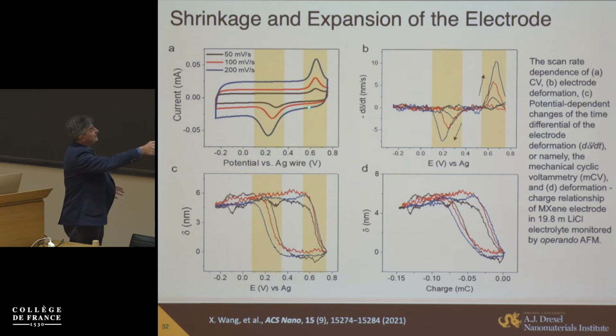And then when potential decreases to roughly 0.4 volt, starting here, they go in again, opening the structure in a step, forming a monolayer of lithium with solvated water molecules here.